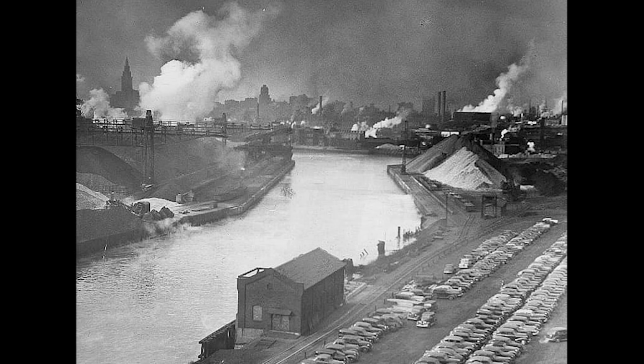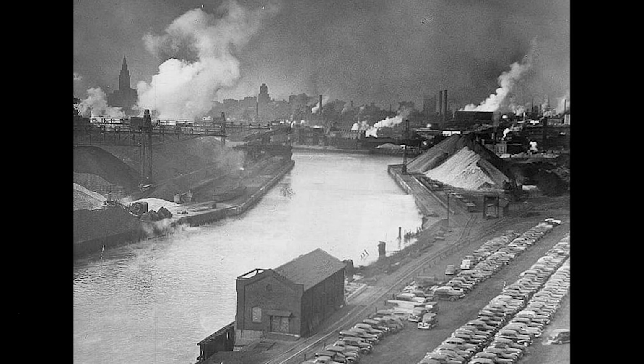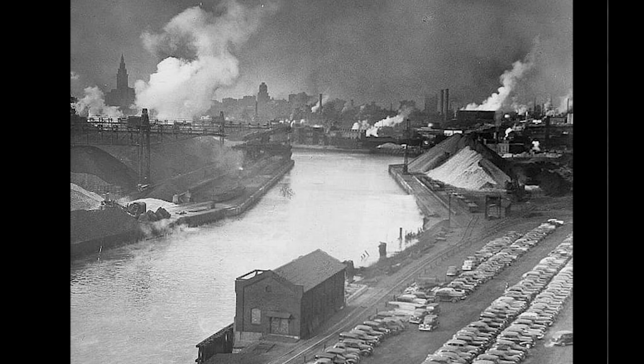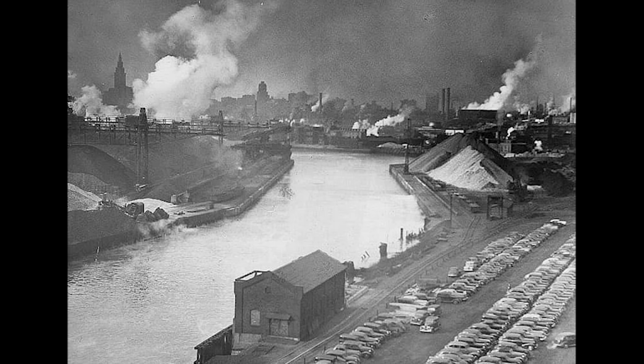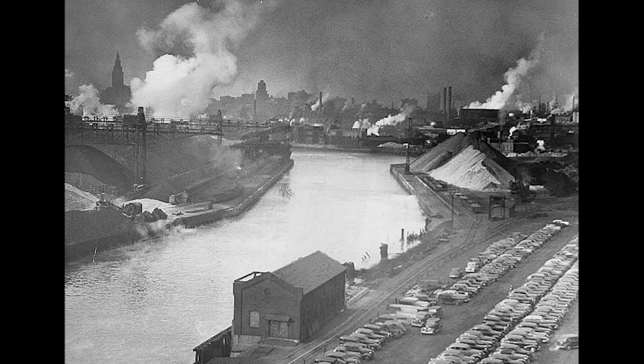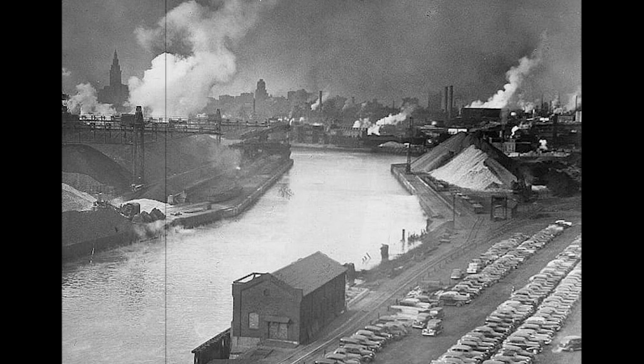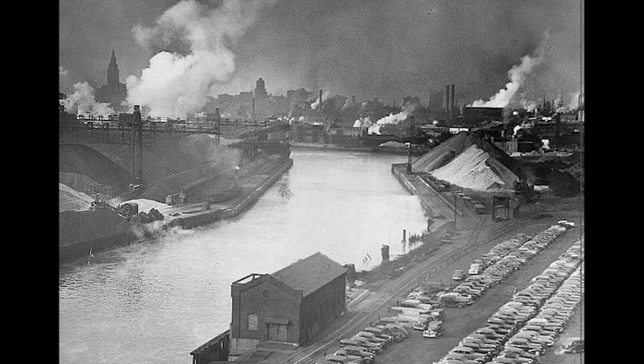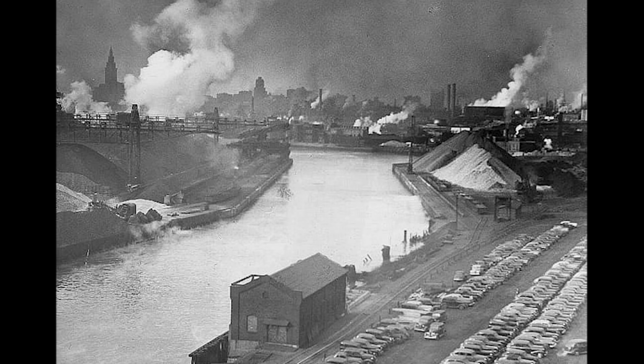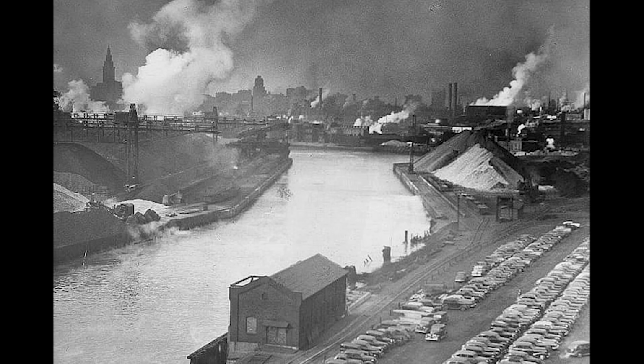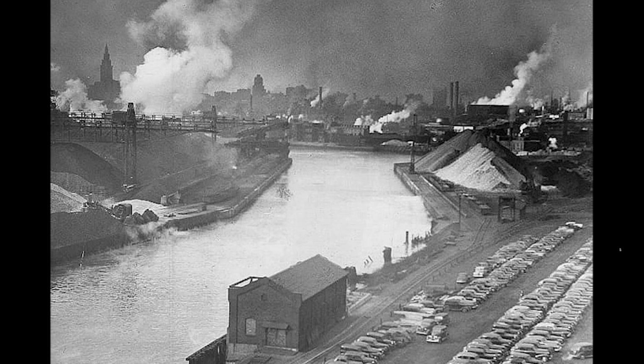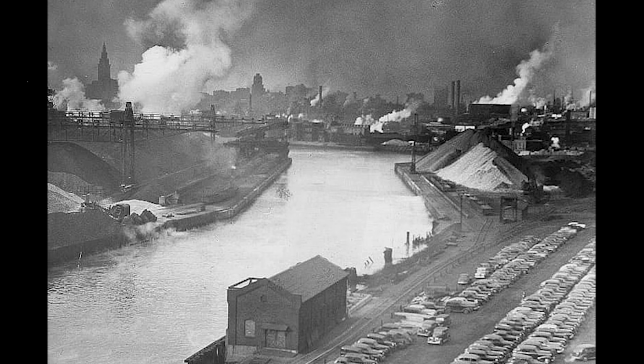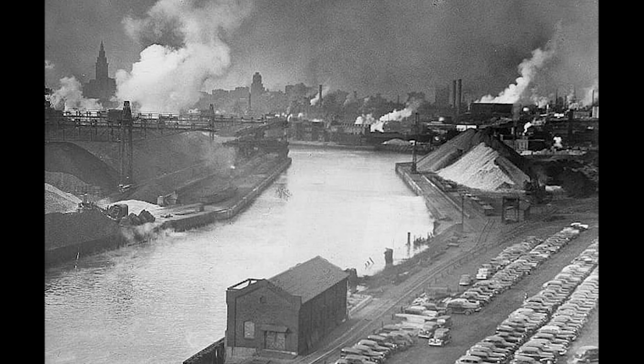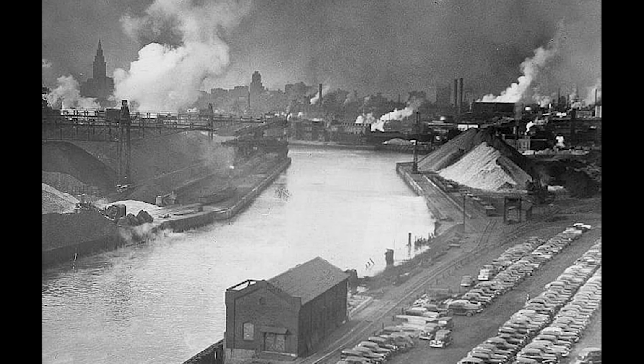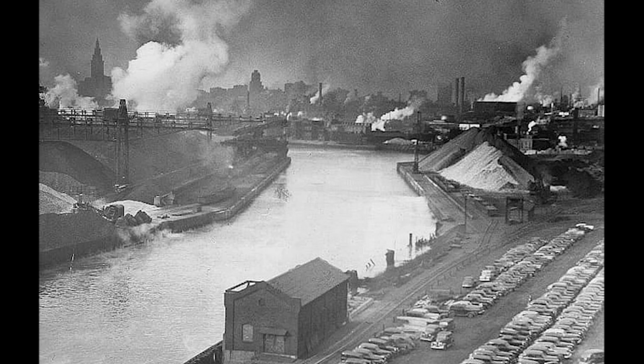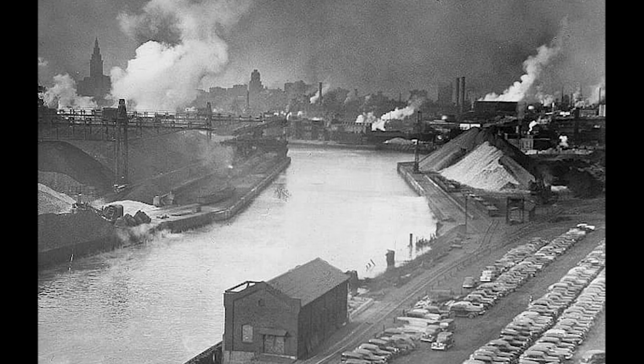While European masters guarded their successful techniques as trade secrets, Lake documented both failures and successes with equal precision, building comprehensive understanding of vanadium behavior under controlled conditions. The experimental process revealed complexity that European guild training had simplified through centuries of trial and error refinement. Lake discovered that vanadium steel's response to heat treatment varied significantly based on ore source, carbon content, and even seasonal humidity changes in the factory atmosphere.